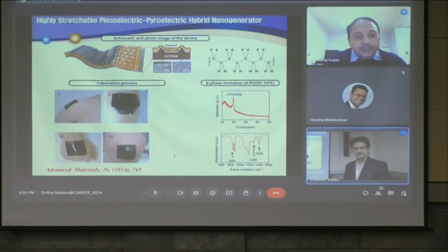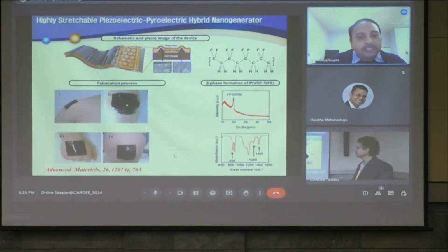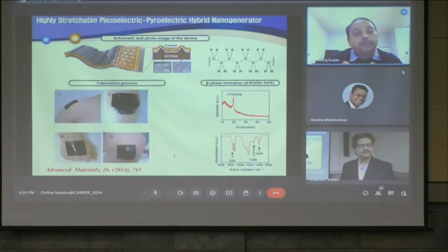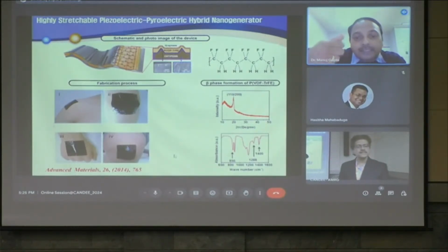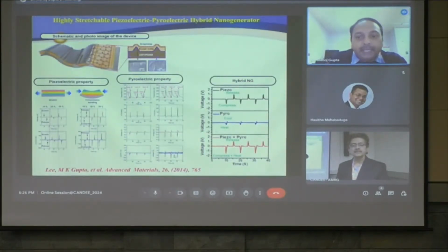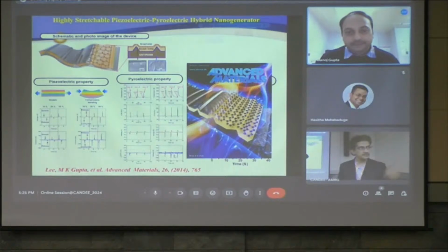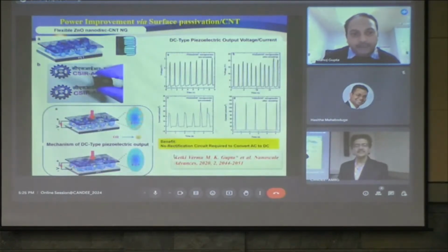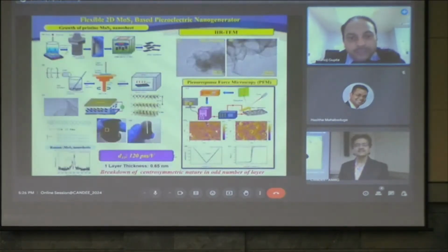So this kind of stretchable devices we have developed by using graphene as the top electrode and carbon nanotube as the bottom electrode, so that heat can directly change the electric dipoles within the system. And at the same time, pyro and mechanical energy both can be integrated together, and that can be wearable also. You can basically wear it. Okay, time is very limited, so I am going very fast.